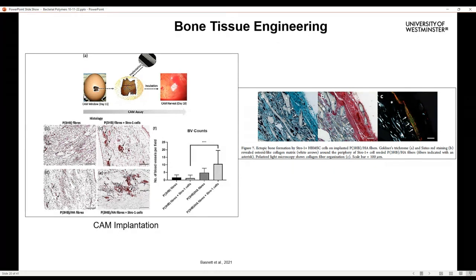It's very important to ensure that the material you're using as a scaffold is non-toxic first. Second, that it promotes blood vessel formation. So we placed this little polymer scaffold, the bacterial polymer scaffold, on top of the membrane of a developing chick embryo and incubated that for 8 days, and we looked for blood vessel formation. And as you can see in this graph here, we were able to report the presence of blood vessels. We then put this in mice again, and I'm not sure if you can see this image clearly, but you can see these little white arrows that show the presence of collagen formation.